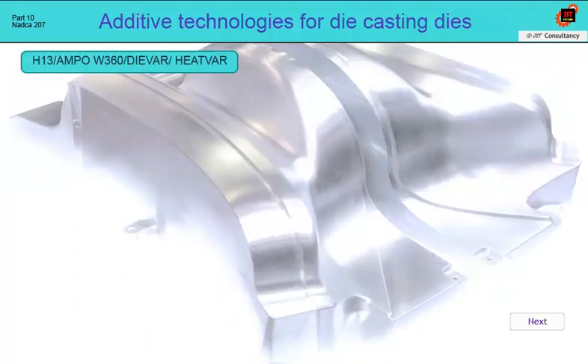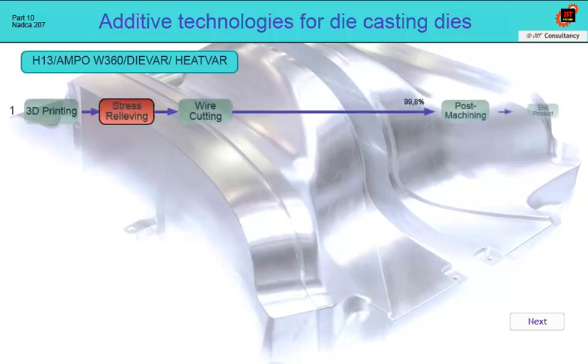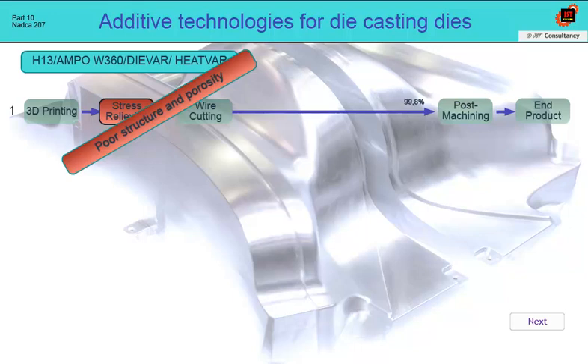In the case of printing material H13, AMPO W360, DIEVAR or HEATVAR, the following procedures are possible. The first process flow involves only printing and stress relief annealing. The printed part is used without quenching and tempering, with a structure corresponding to the annealing process. The part properties depend on the powder quality, printer, printing parameters, printing strategy, platform temperature, and many other parameters, and it can be assumed that the structure will contain a high amount of only once-tempered martensite and a large portion of residual austenite, with very negative properties to meet the thermal fatigue resistance requirement.